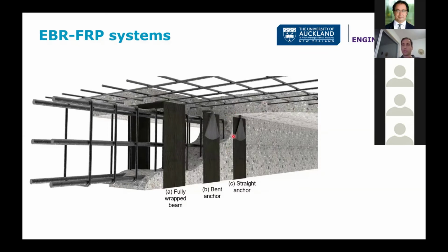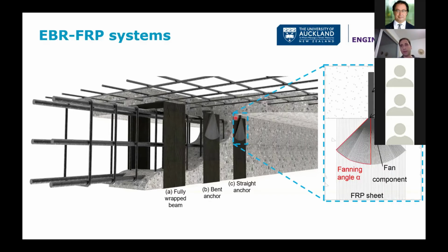So we are not using the material efficiently. One way to overcome that premature debonding failure is FRP anchors, which are just bundles of fibers that are soaked into epoxy, and then one end is introduced into the concrete, into the slab in this case, if we are using straight anchors, and the other end is fanned out and bonded to the FRP sheet behind. So we have the dowel inside the concrete and the fan outside.